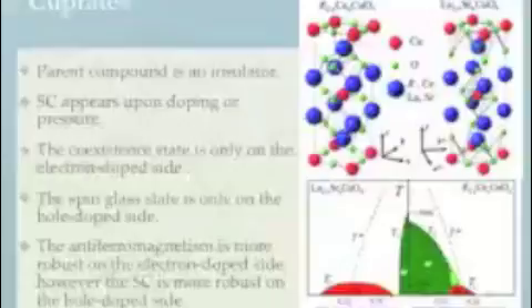The dashed green line indicates the pseudogap phase transition. The origin of the pseudogap is still not clear. There is a spin glass on the hole-doped side, which is not shown in this phase diagram. But the spin density wave has never been detected on the hole-doped side. The coexistent state only happens on the electron-doped side. It's never been detected on the hole-doped side. The light green region is the possible area for Néel temperature. People still don't know what exactly causes the asymmetry in the phase diagram. It's a very intriguing question.